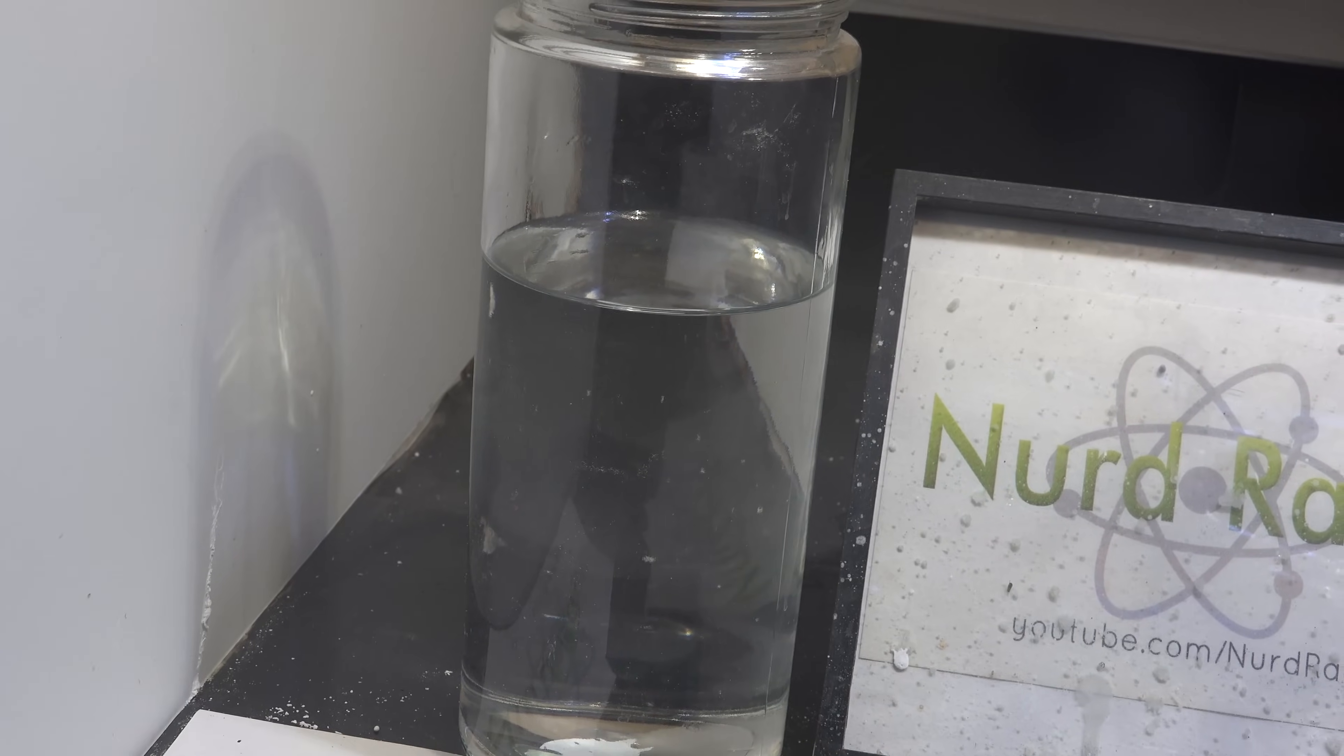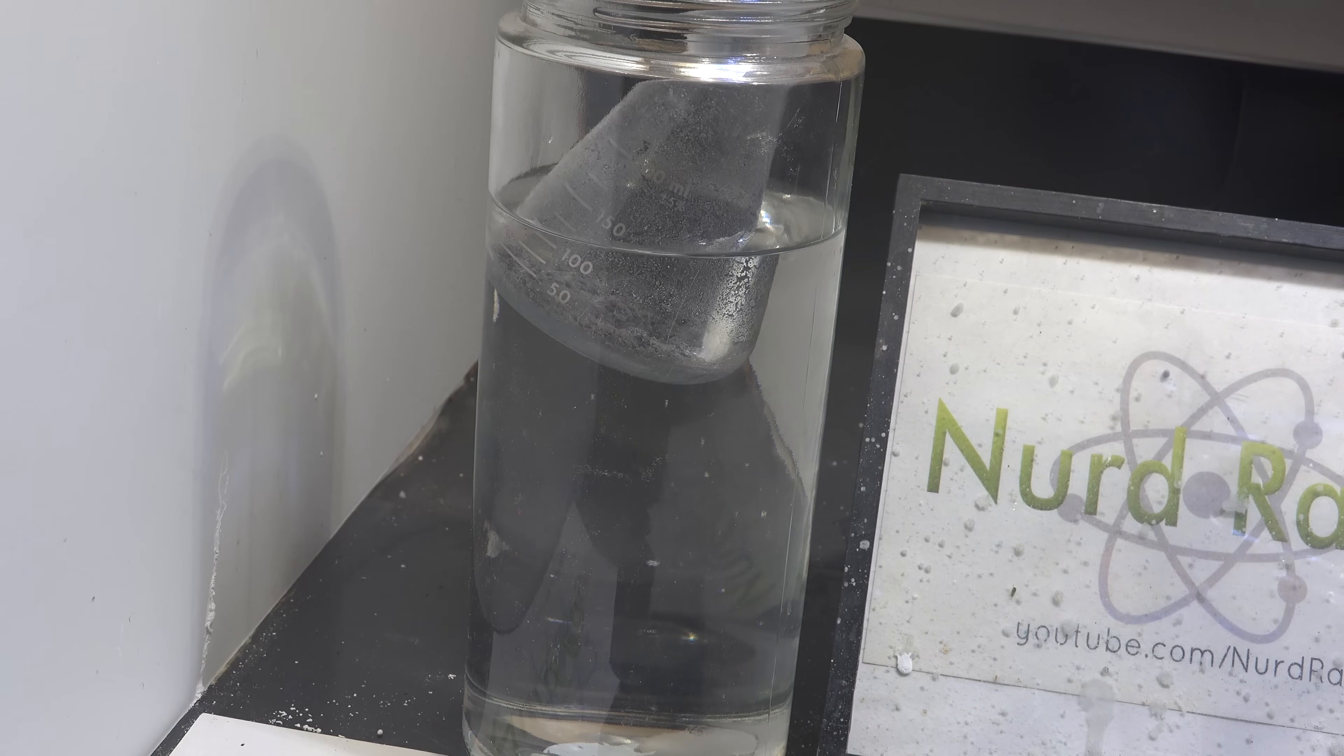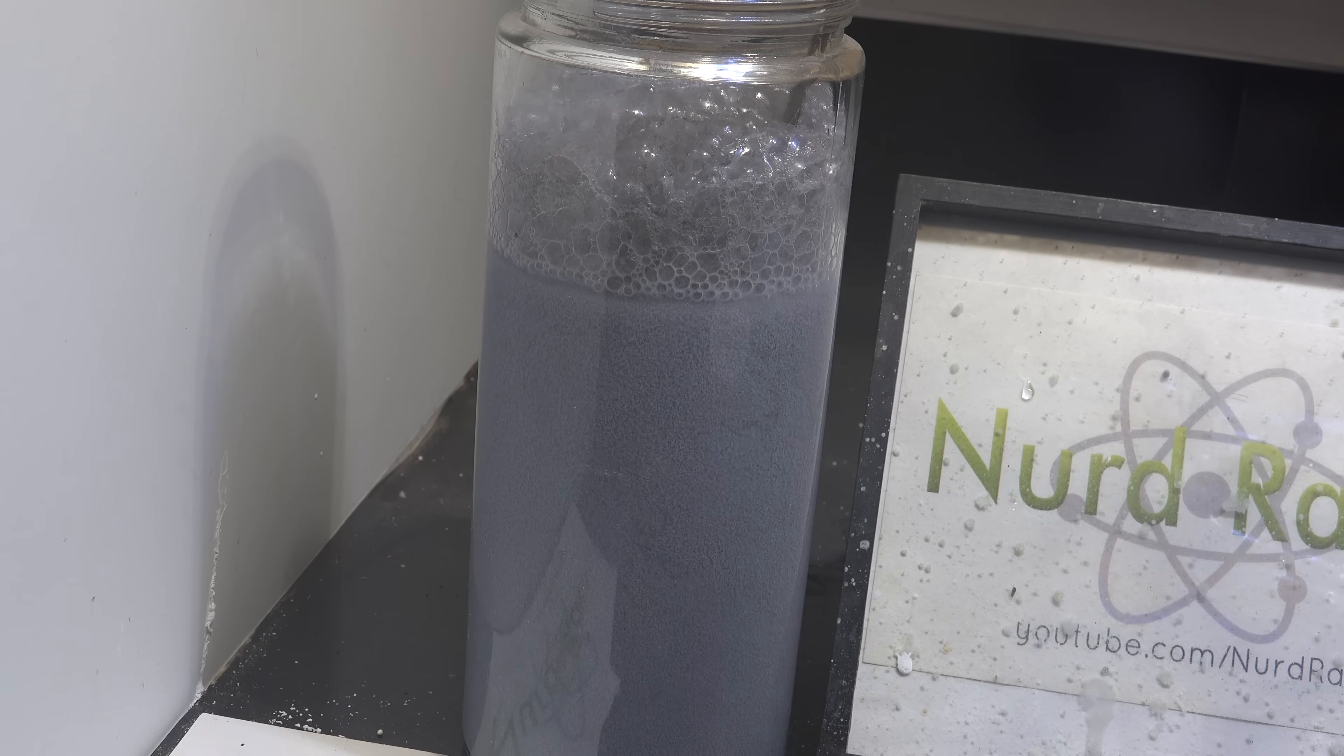Now after recovering the sodium you'll need to neutralize the slag now that it's caked into the flask. Get a tall container of water and push the flask of slag down into it with a rod. I don't recommend using your hand directly in case there are leftover exploding bits of sodium. We're doing this to destroy any remaining leftover sodium in the slag so it's safe to toss it in the trash. Last thing you want is your trash on fire. We're using this much water to absorb the large amount of heat generated by the reaction. Leave it in there for a few hours to make sure all the slag is destroyed.